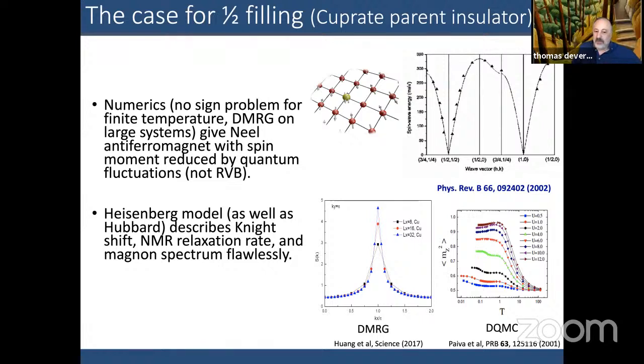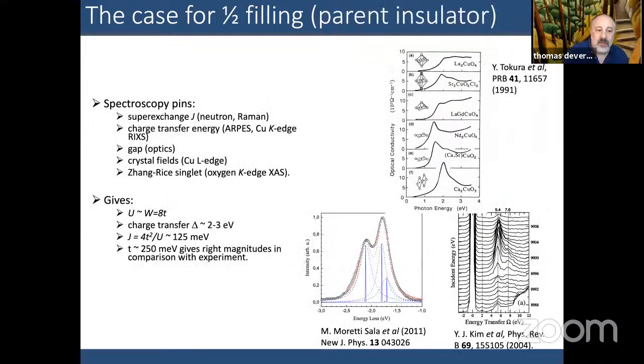The Heisenberg model does a very great job of describing the magnon dispersion, the Knight shift, the NMR relaxation rate. I would say pretty much flawlessly. And if we look at the results compared to spectroscopy, we can pin various different parameters that enter into our Hubbard model. So there's the optical conductivity. This gives us an estimate for the charge transfer energy. The value of the magnon dispersion gives us an estimate for the superexchange J.